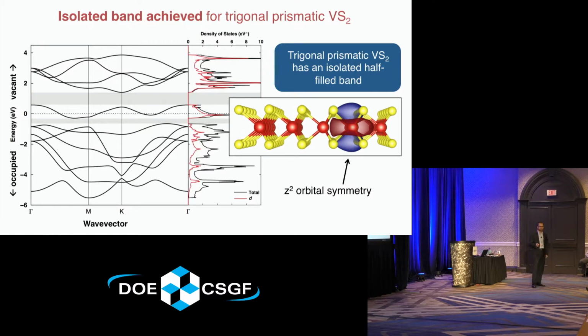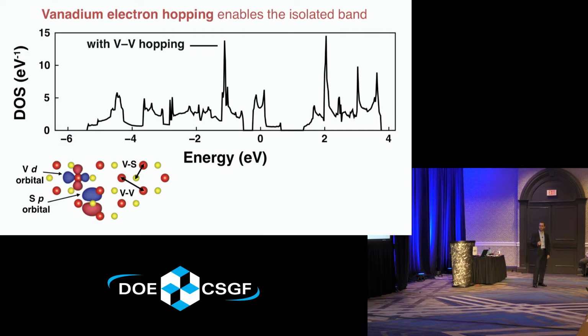electronic structure. Now, one of the nice things about theory and computation is that we can actually, at the microscopic level, really gain an understanding of the physics of these things. And so we can basically turn on and off different orbital interactions, for example, between the vanadium orbitals and the sulfur, and the vanadium-vanadium interaction. And you can see here, this is just that spectrum turned sideways, that here with the vanadium-vanadium and vanadium-sulfur interaction, we're qualitatively reproducing this feature. We have this single isolated band.